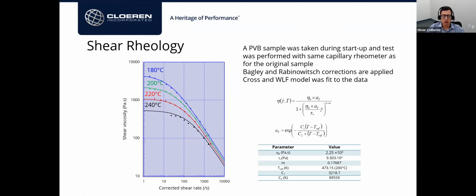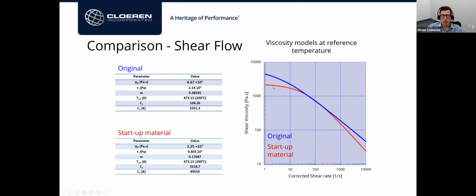Lastly, I was there at startup and picked up some material and remeasured this material in my rheometer. Instead of 3 temperatures, I did a 4 temperature characterization and applied, again, the Cross model. And what was interesting is that PVB is actually a plasticized material, and coming from the twin screw extruder, I believe that how that plasticizer is distributed or mixed can have some influence on the flow behavior.